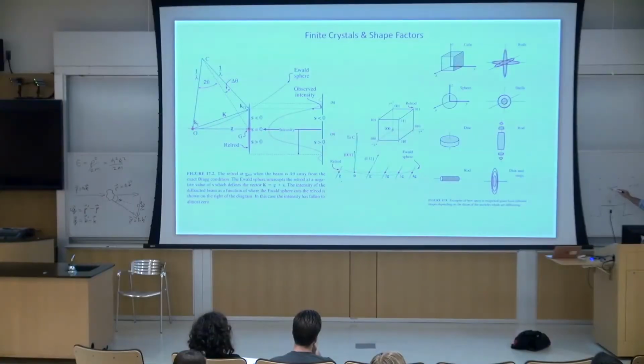If I multiply things in real space, what happens in reciprocal space? They get convolved. So if I want to ask what happened to my beautiful diffraction pattern with its nice sharp spots, I go to Fourier space, and I have to convolve the Fourier transform of my lattice with the Fourier transform of my shape.